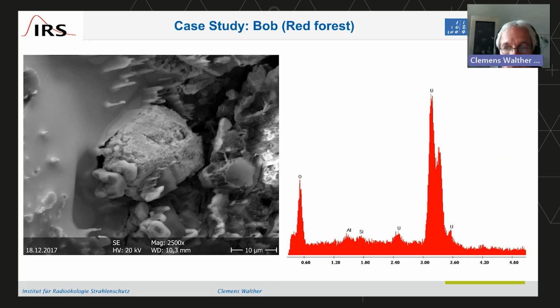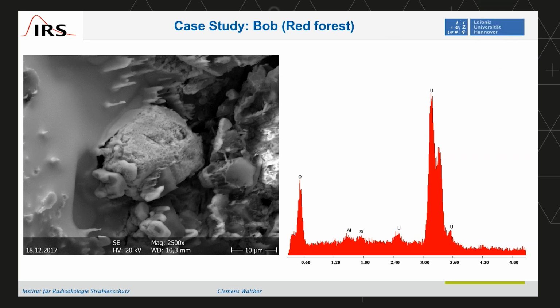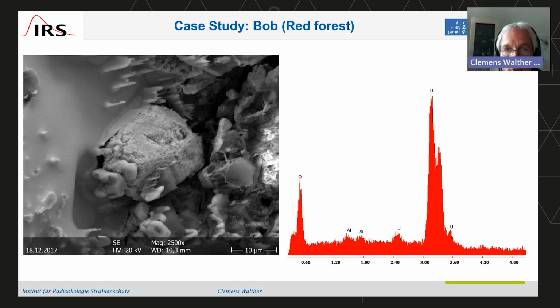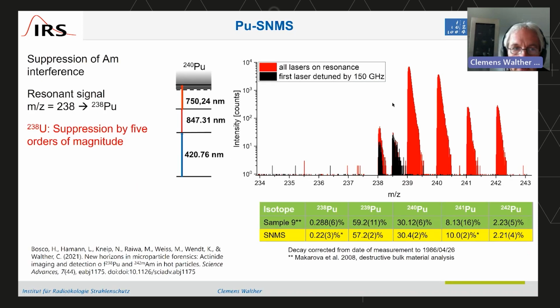So coming back to our case study, we just assume we singled out a particle from that dirt, and now we're going to investigate this particle. What we first do, since it is in the electron microscope anyway, is an EDX. The EDX gives you first information on the elements. Of course it contains uranium and oxygen, so that gives you a hint that it indeed is nuclear fuel. We have some aluminum and silicon on it, but that might be due to the substrate here.